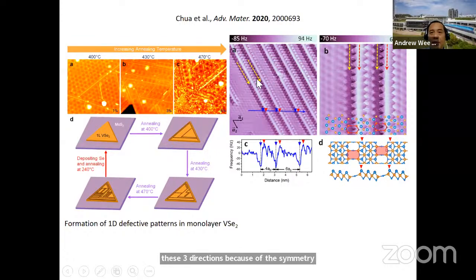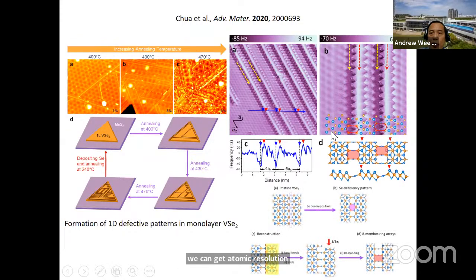And if you look at the surface carefully using AFM, and we can get atomic resolution of the surface, we can build up an atomic model of the surface. And you can see these missing rows are due to missing rows of selenium. And these missing rows have an 8-member ring here, which we attribute to a shift of half a unit cell of one side of this line. In other words, we create a reconstructed surface with a line defect.